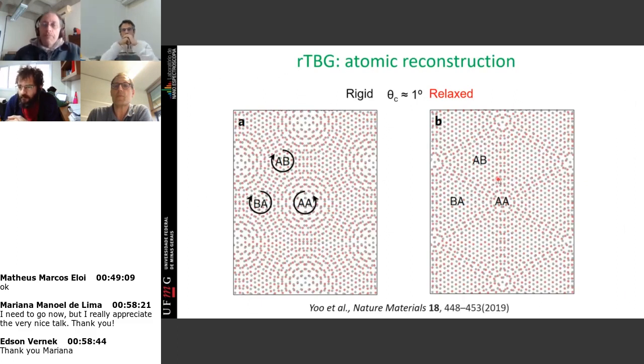Look, let me put it this way. They are all localized, but there are three very different situations here. One situation is the usual A-B stacking. The other situation is the soliton of strain here, where there is a strain that modulates from here down there. And you are right that there is a quite strong interaction in these AA regions, because this is where one atom wants to be exactly on top of the other. And this is very unlikely, very unstable, very bad for the atoms. And this is where the strong localization happens, and this is where the flat bands appear.